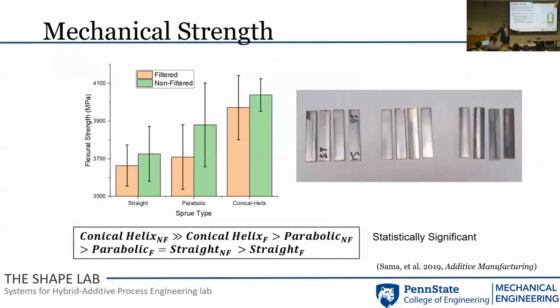And our hypothesis is because we are reducing the velocity that we were able to do that. But again, micro-CT is slightly better than CFD-only results, but you still need ground truth results. So we did 3-point bending tests again, with and without filters as well, to see what the evidence was. And with statistical significance for steel, we found a 14.7% increase in flexural strength.